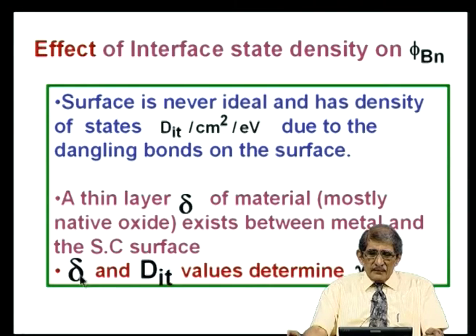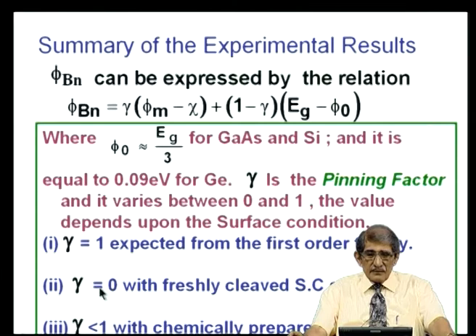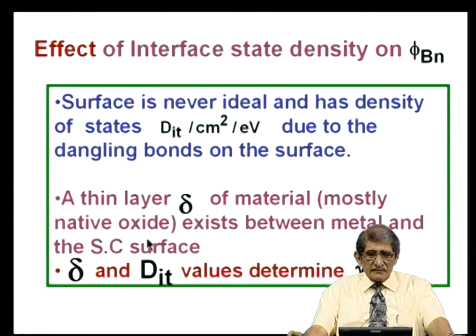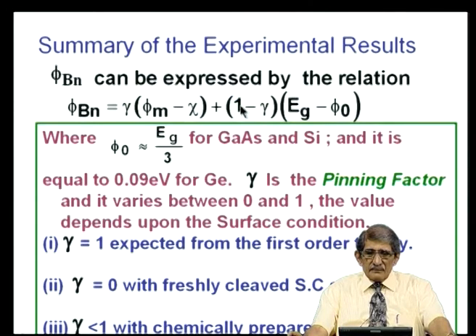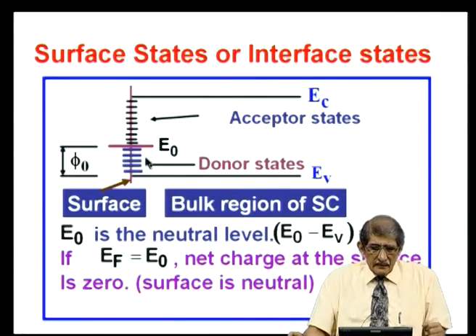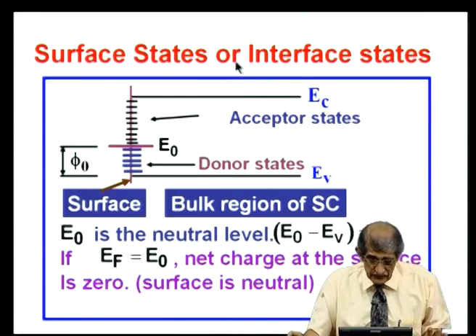So, dIt and delta values determine gamma. The deviation from the ideal is due to the presence of some thin layer and the interface state density. Those two are responsible for giving rise to this gamma. Ideally, delta is 0 and dIt equals 0, you will get gamma equal to 1 and you get phi minus chi. This we have seen in detail, I do not have to go through that.